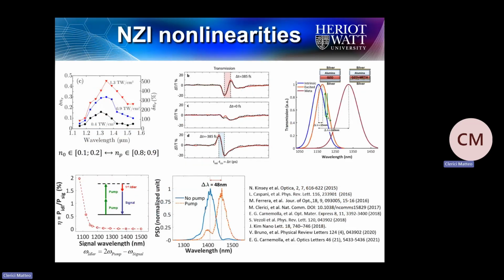So let's talk about a few preliminary results, those that started a lot of discussion behind the nonlinear application of these compounds. Here are just a few that I actually like very much. The first one demonstrates how much the refractive index of this material can change. As you can see, it's massive, not just in percentage because you start from a low index, but it is very large in magnitude. Here we show almost a unitary change, but recent works show that this can be pushed considerably higher than 1 in terms of refractive index. So you can even easily match the refractive index of air.